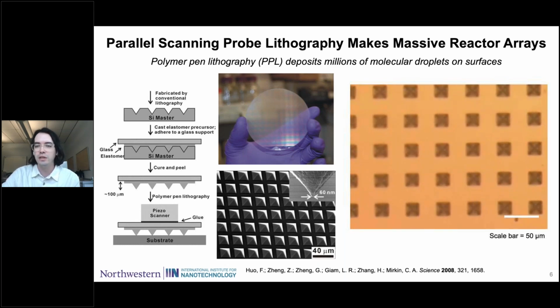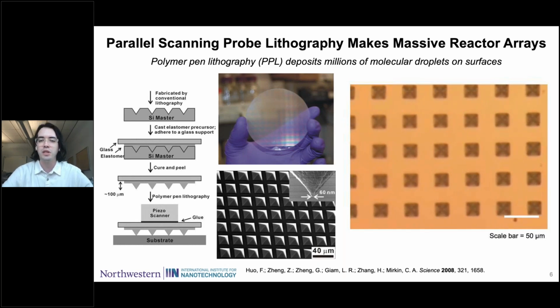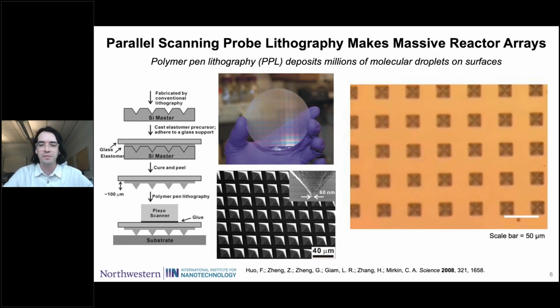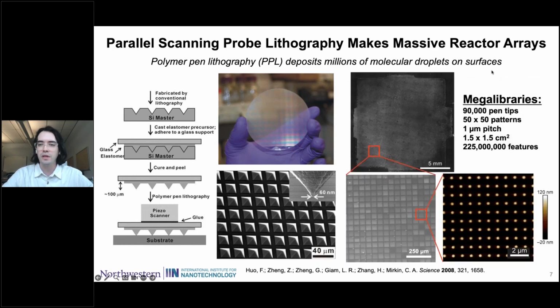In this video, you can see what it looks like when we're actually patterning on a surface. Each of these squares is a pen tip, and we're viewing from above as they go up and down and touch the surface. You can see the light changes when the tips are touching the surface and they're being slightly deformed. As they touch the surface, they're transferring molecules from the tip to the surface. If you do this patterning in just under 30 minutes, you can generate a Megalibrary with a centimeter-sized array with, in this case, over 200 million features of these droplets.